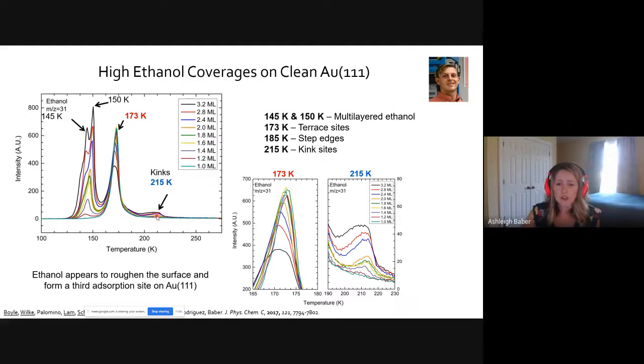If you take a really close look at that trend, as we add more and more ethanol, here, if you look at this black line, 3.2 monolayers, we actually see that the terrace, this is the 173 Kelvin peak, has actually decreased in intensity. But this peak at 215 Kelvin has increased in intensity, almost as if we're taking what used to be ethanol adsorbed to terrace sites, and now we are changing that concentration so that we have more desorption from these molecules that have been adsorbed to under coordinated sites.